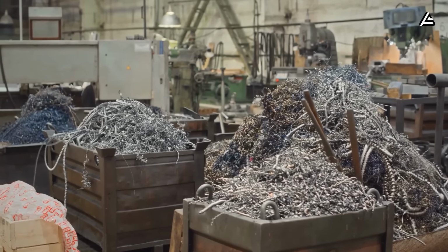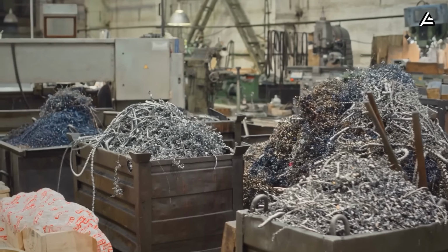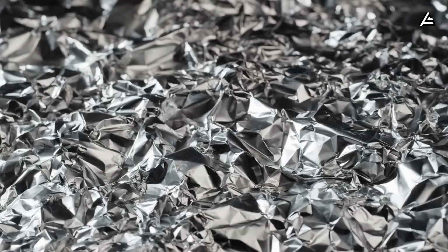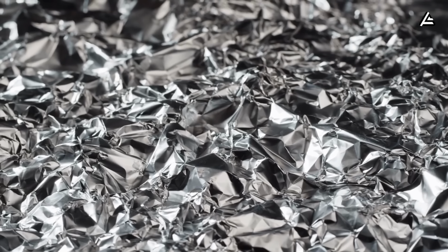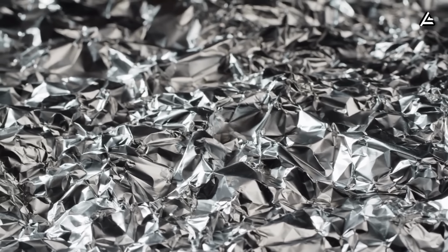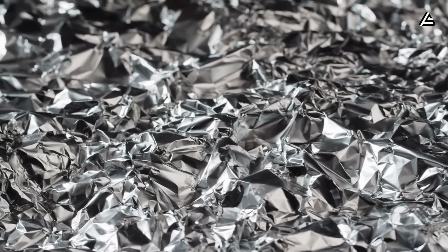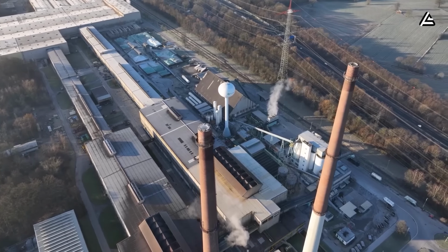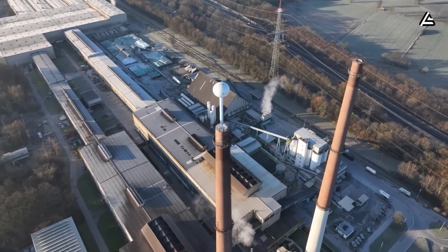Aluminum is already the most recycled industrial metal on the planet, with recovery rates above 90%, which means that for every 10 tons of aluminum discarded, at least 9 tons get recovered and reused. Refining recycled aluminum consumes only 5% of the energy required to extract new metal from bauxite ore. In other words, it cuts power use by 95%, saving about 14 megawatt-hours of electricity per ton. For context, that's the same energy a Tesla supercharger station uses to charge 70 cars to full capacity.